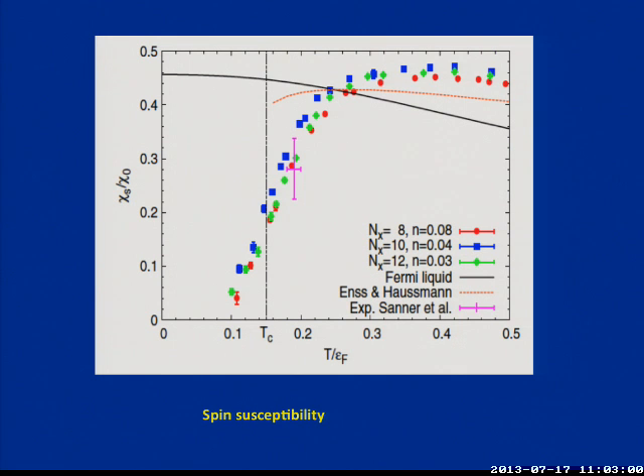So now if you look how this spin susceptibility goes, it goes from 0, goes to the critical temperature very smoothly, it doesn't care. And it becomes that of a normal Fermi fluid at temperatures well above the critical temperature, basically where the pseudogap disappears. So this is consistent with the fact that in a unitary gas, pairs survive, the Cooper pairs survive the critical temperature, unlike the BCS. They exist at finite temperature.